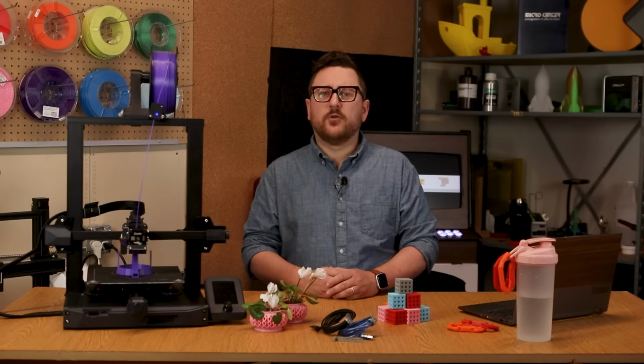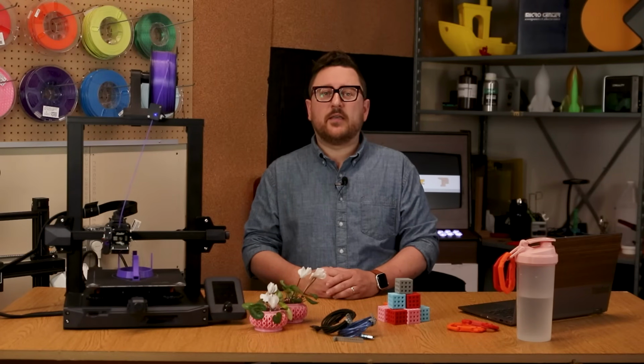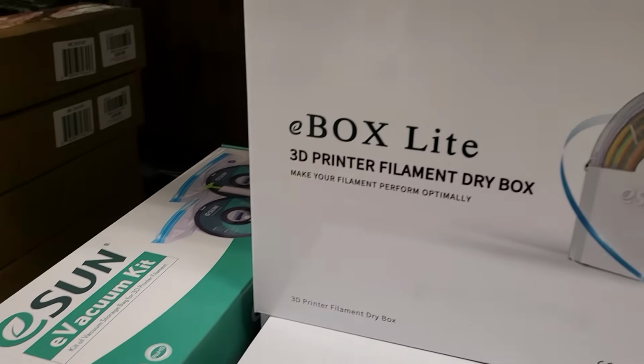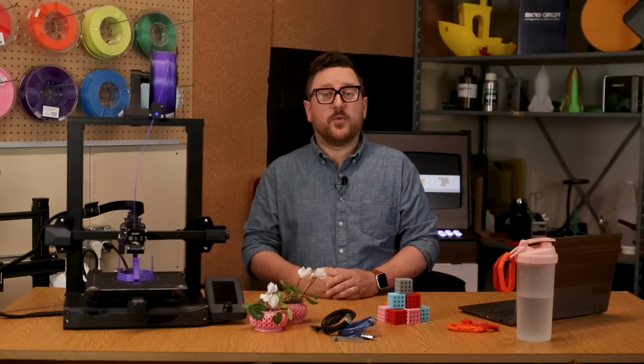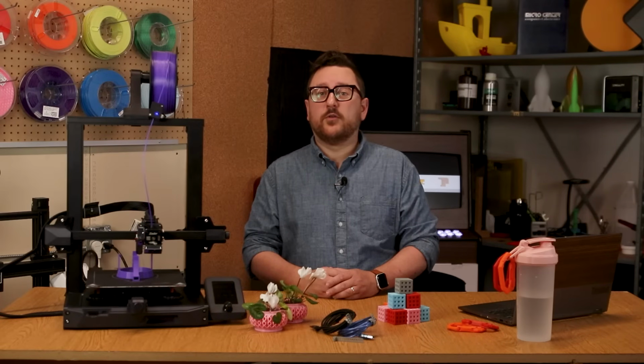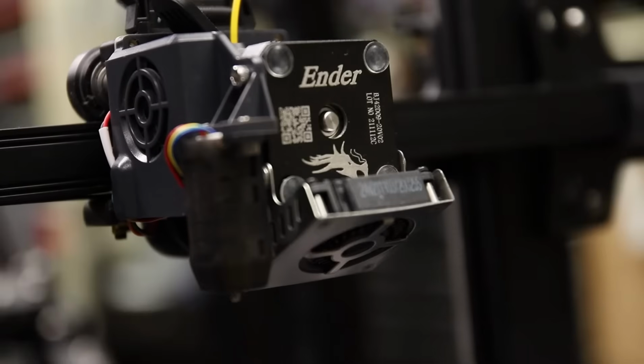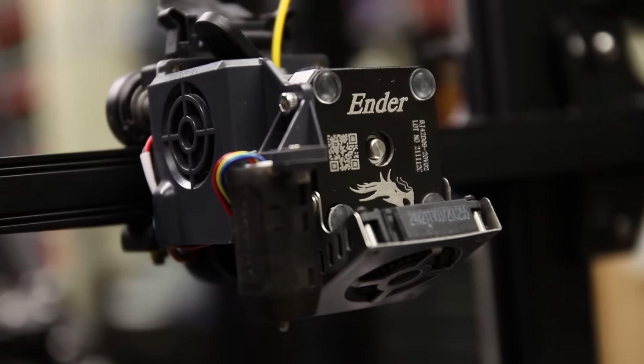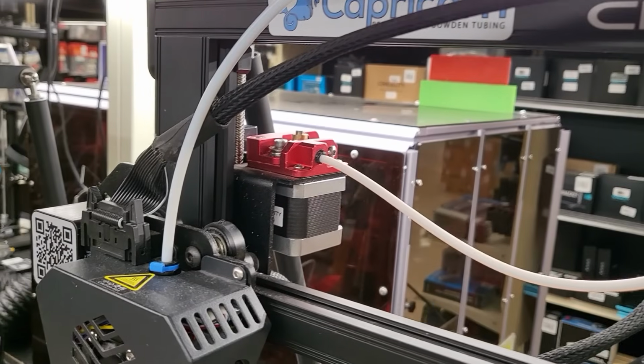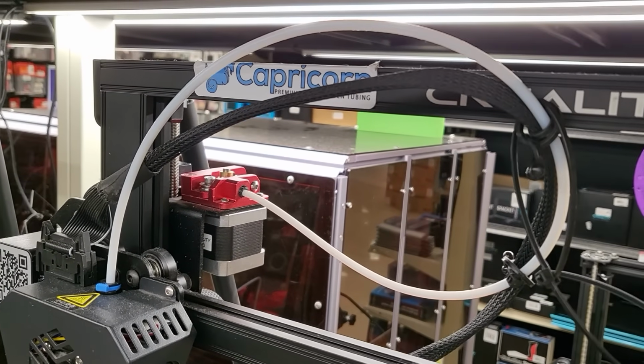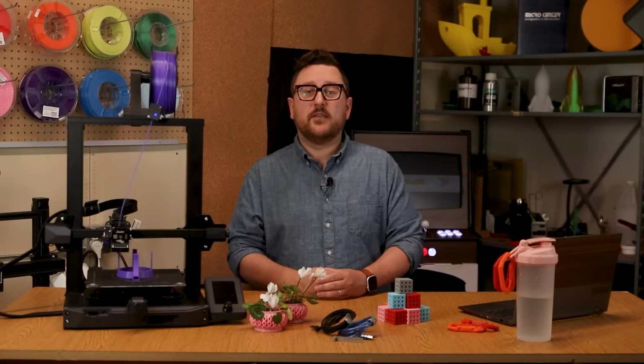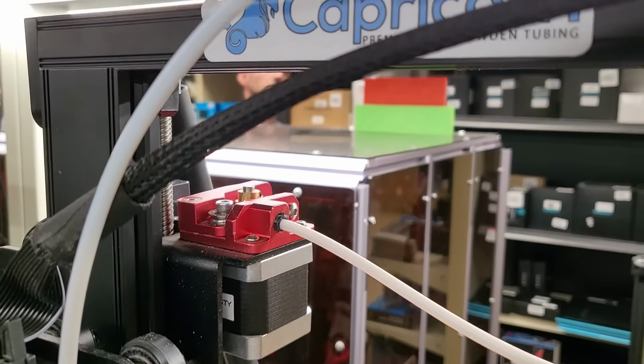TPU is also prone to absorbing excess moisture and should be kept in a sealed bag with desiccant when not in use. It is possible to dry out filaments when they absorb moisture, but that's a topic for another day. For TPU, it is also good to consider printing with a direct drive extruder versus Bowden tube style, as the flexibility of the filament can potentially become jammed in the distance between the extruder motor and the hot end on Bowden style printers.